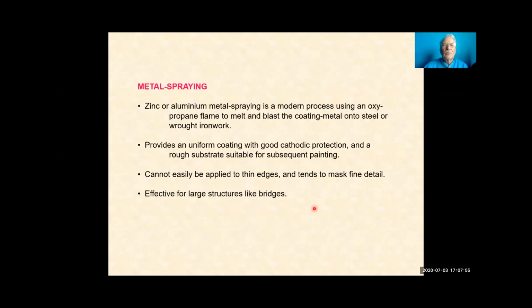My questioner was asking previously about metal spraying. This is a very good process. You have to blast clean the metal completely clean to start with, and then you can use an oxypropane flame to actually put a spatter of zinc or aluminium onto the surface. It can be quite thick and it's very effective, so you get this cathodic protection.